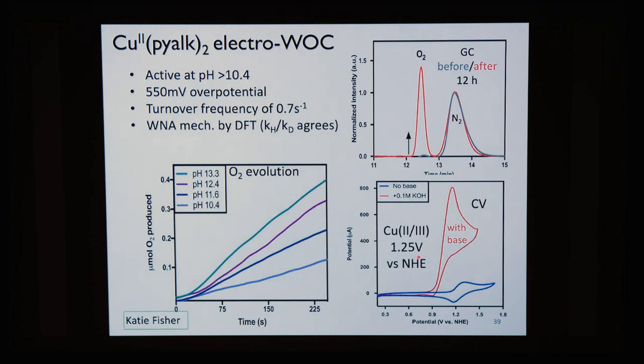And again, water nucleophilic attack mechanism by DFT with the KIE agreeing. And she was also able to show that the more basic she is, the more we get of oxygen. And then detecting the oxygen here by GC. And here we have the complex in the absence of water gives a nice reversible peak. And then with the base present, we get the catalytic wave.